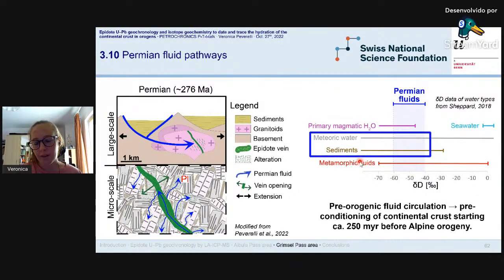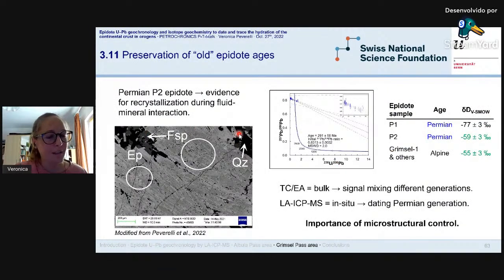I would like to stress once again that the fact that we have evidence for pre-orogenic fluid circulation implies that the preconditioning, so the weakening of the granitic continental crust in the European passive continental margin, started about 250 million years before the involvement of the continental crust in the alpine orogeny. So it's quite important. Something that I personally really like about one of the Permian samples is that if you look closely, you see that it has a funny microstructure that suggests epidote recrystallization during fluid-mineral interaction.